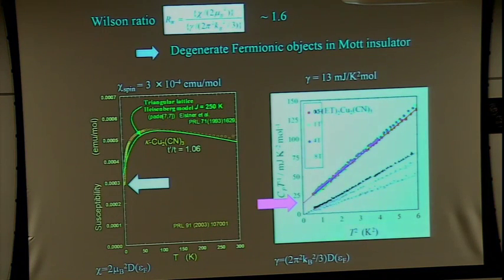Okay, this is a comparison of the spin susceptibility and the specific heat gamma. The gamma is 13 millijoule, and the low temperature limit of the spin susceptibility is roughly 3 times 10 to the minus 4. The Wilson ratio characterizes the degree of the Fermi liquid. For example, in a free electron gas, chi is expressed as this: this is the Pauli susceptibility, and this is the free electron gamma value. So the Wilson ratio R_W should be unity for non-interacting electrons.